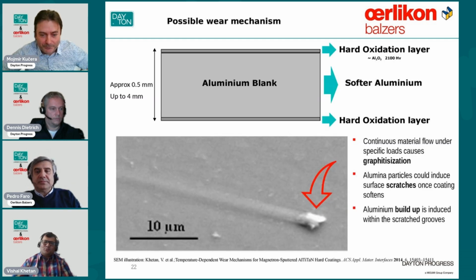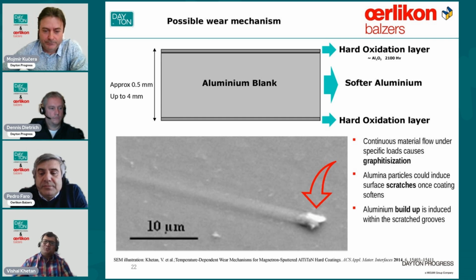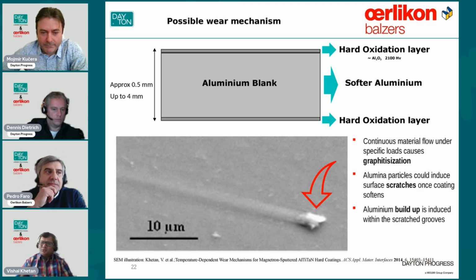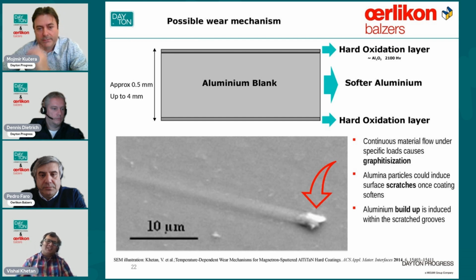Thank you, Mohammed. So in our coatings world, we look at the wear caused by aluminum stamping onto the tool in quite some detail, and we try to study it as well as possible. As Dennis was already explaining, whenever you stamp or punch an aluminum blank, you typically always have a residual oxide on top of these blanks, which can form, and this is just an example illustration here, some kind of hard particles which then start to scratch the tool.